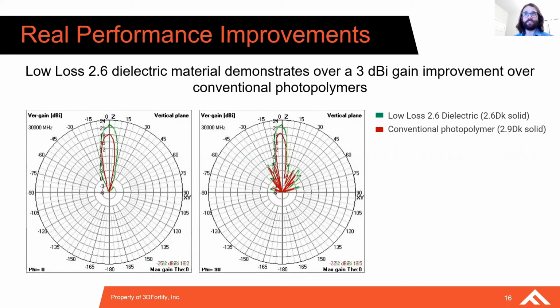The radiation patterns you're seeing here on the left of the screen show the comparative result between two lenses. The one I mentioned, manufactured from the conventional photopolymer material, is represented here by the red curve, while the low loss 2.6 DK material is shown in the green curve. And by using the low loss 2.6 dielectric material, we're able to realize a 3 dBi gain improvement over the conventional photopolymers.